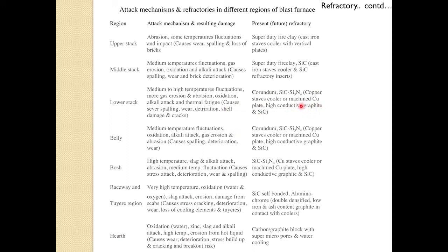In the belly region, medium to high temperature, alkali attack, and gas erosion occur. Machined copper plate cooling with high-conductivity graphite or silicon carbide brick is mostly used. In the bosh region, high temperature slag and alkali attack are predominant with medium temperature fluctuation. Silicon carbide or silicon nitride brick with machined copper plate and high-conductivity graphite or silicon carbide is used.